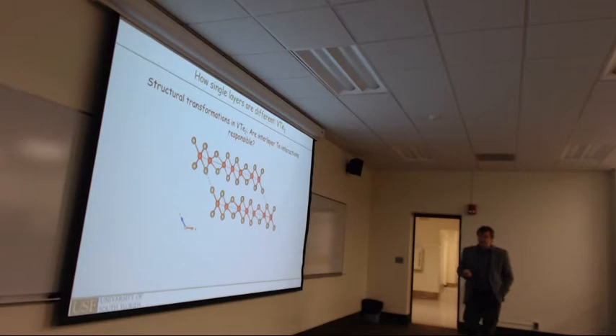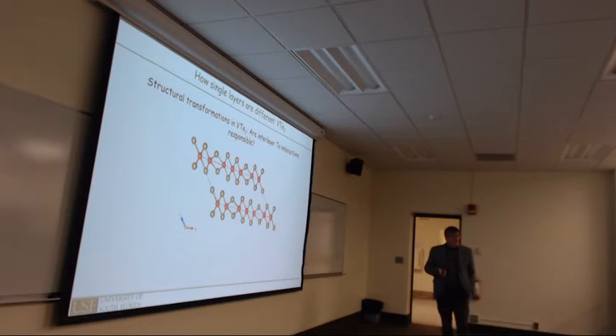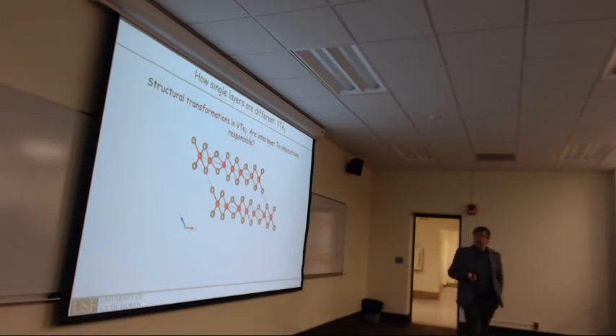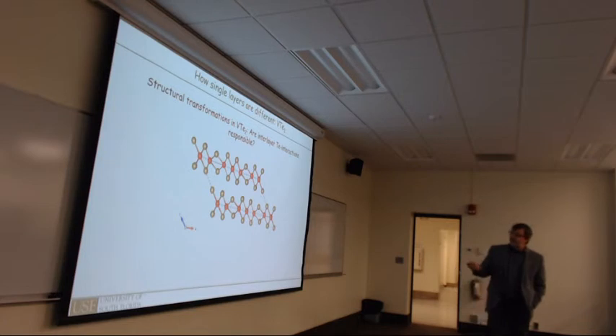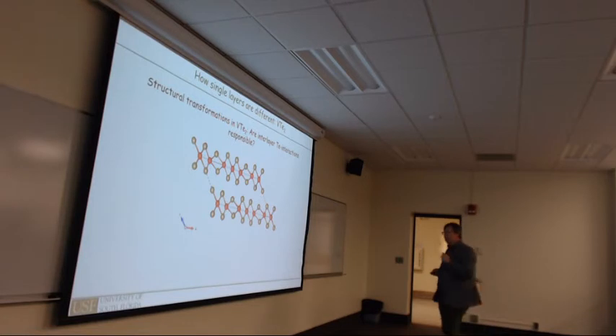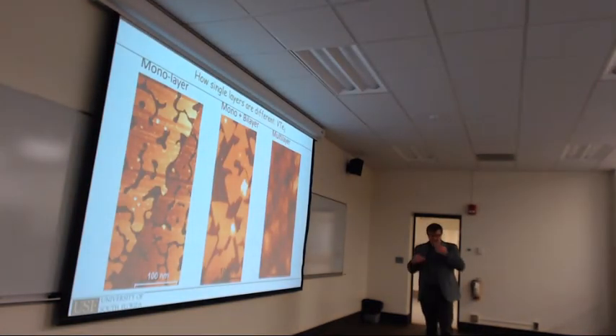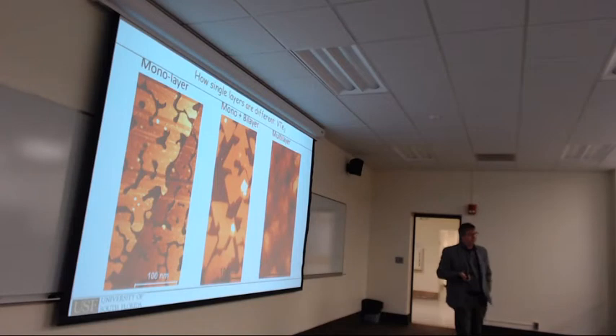And the question is, is this distortion of the vanadium ditelluride structure a consequence of interlayer interactions? One reason why we might think that, from a naive picture, is that if you look at the distortion, it looks like a gear wheel structure where these are the teeth that go into the hole of the other layer, so that allows them to stack differently.